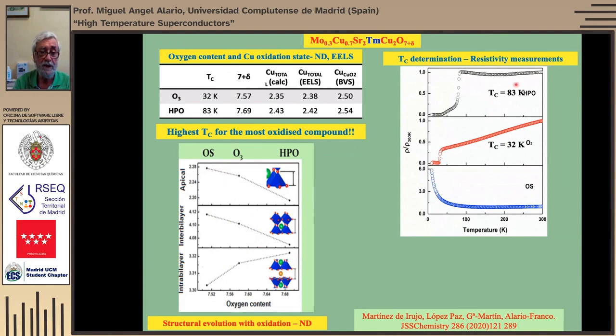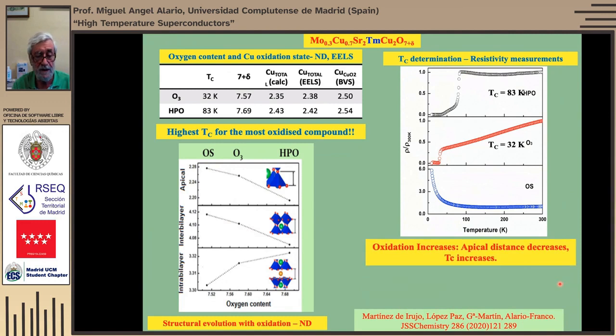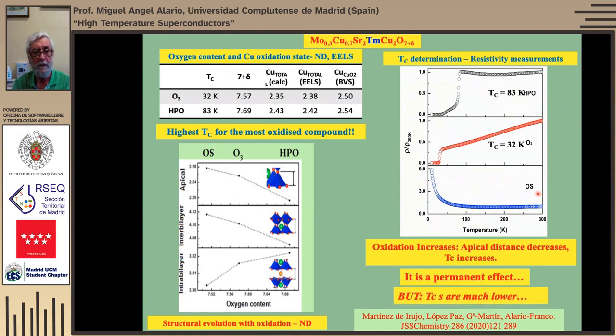And we observe indeed that TC, this is the normal one, simply with oxygen, with ozone, the TC increases, and with high oxygen pressure, we increase further. So this is a permanent phenomenon. With oxidation, the apical distance decreases and TC increases. But it's a permanent effect, but the temperature that we achieve is very low compared with what they do. So we have to work more. I mean, it's a long story, this. It will be too long for me to explain all this.